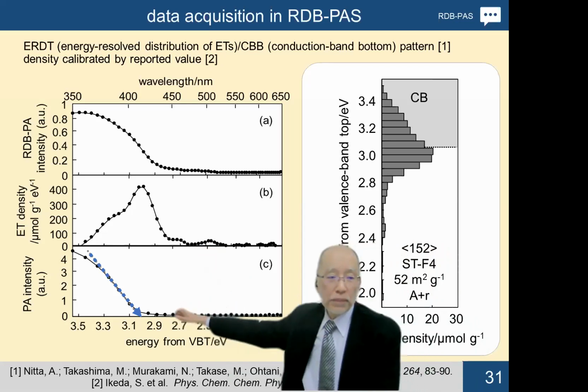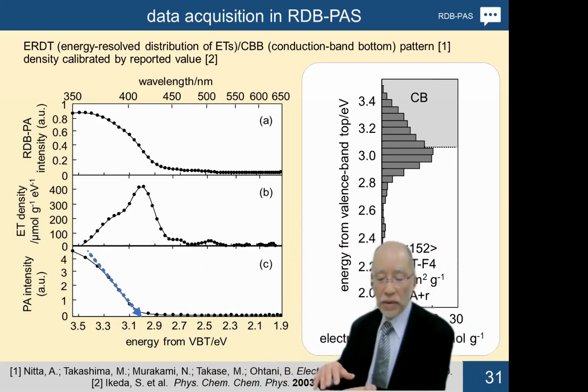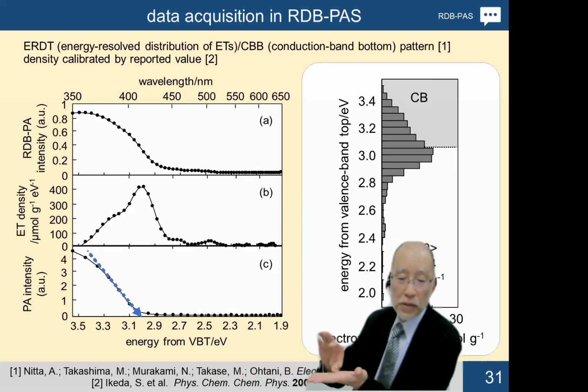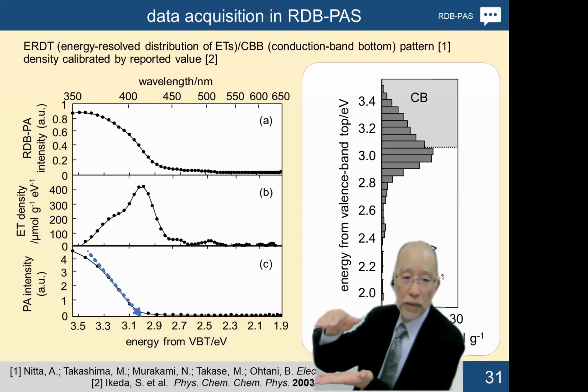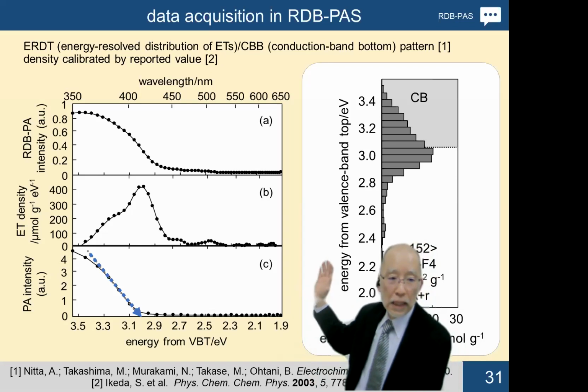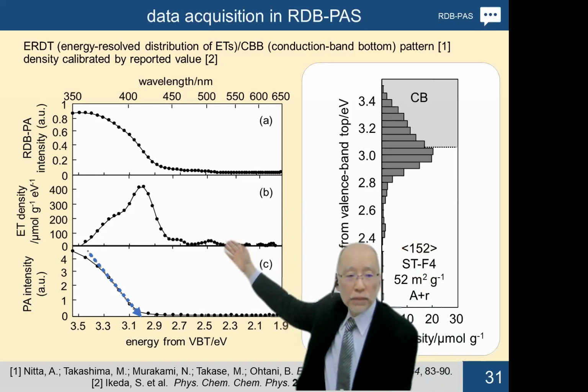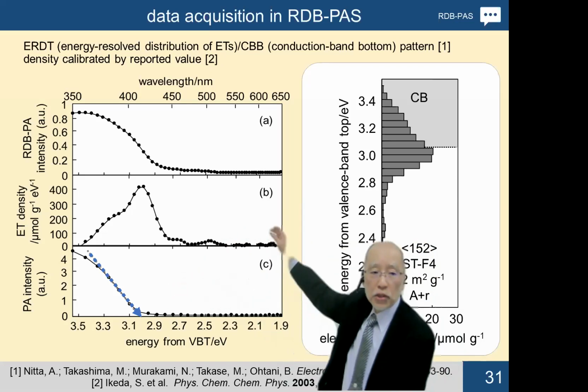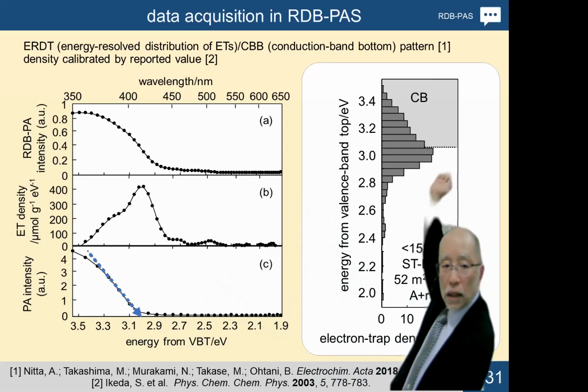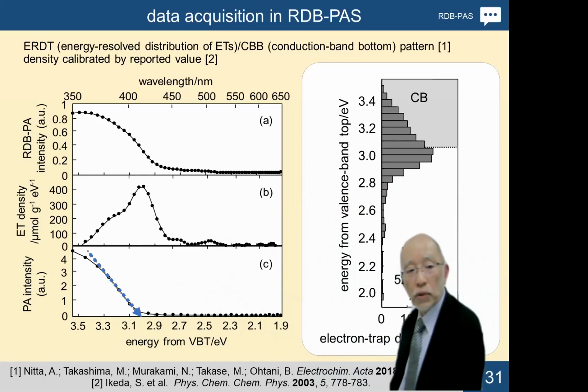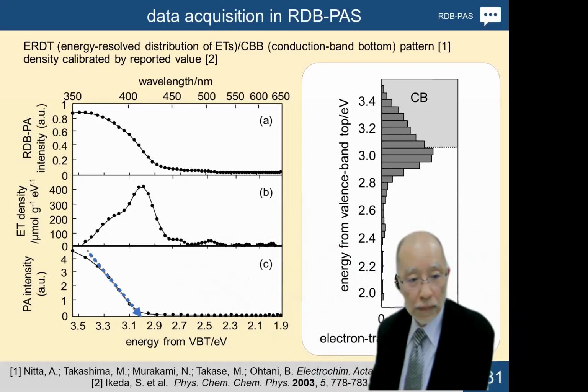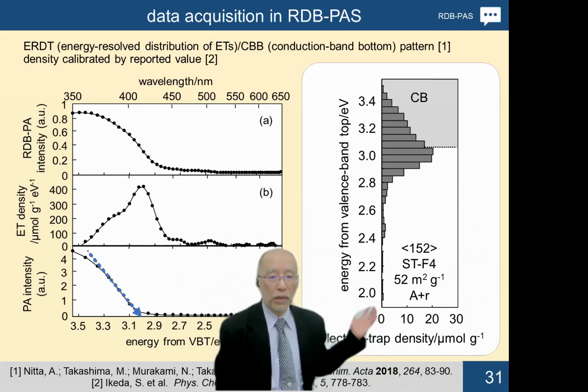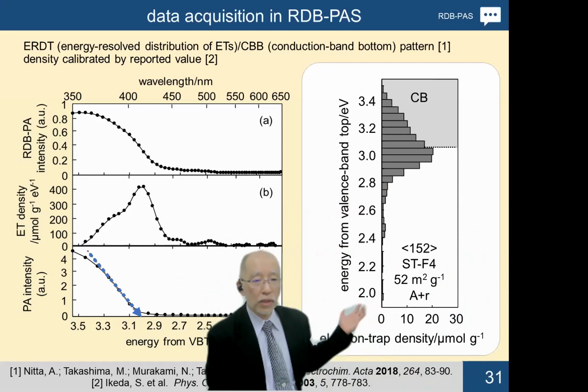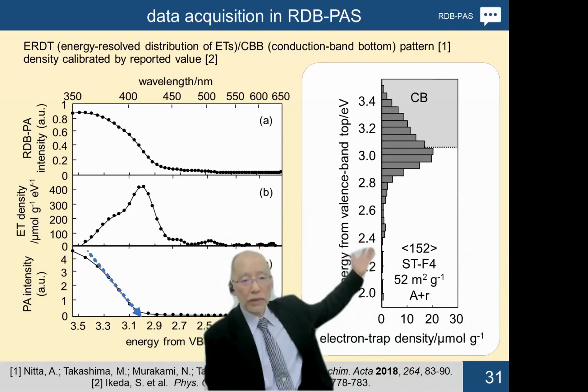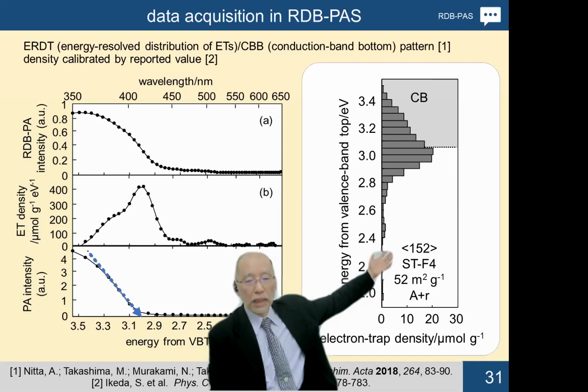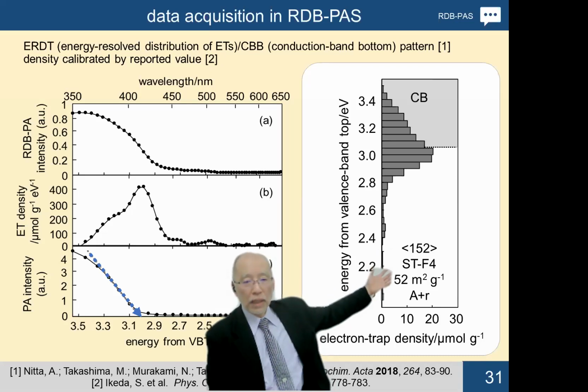And the band gap energy is the energy difference from valence band top to the conduction band bottom. So therefore, same as in this energy distribution of electron trap, the conduction band bottom position can be shown like here in the line. That is the conduction band bottom position in difference to valence band top position. And this is the example of one of the commercial titanium oxide, STF4. And 152, this is the total density of electron trap measured in this technique.